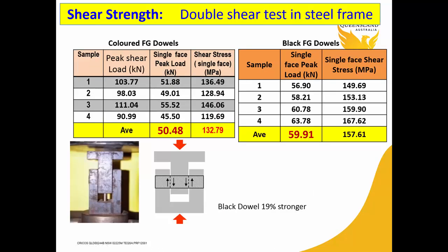Shear strength testing was also carried out in steel double shear testing, as you can see here. The difference between the guillotine box and steel double shear testing is that you have two cross-sectional areas of shearing rather than one, as in single shear testing. The sample is cut to a small length and positioned inside this hole. It goes inside the instrument, and the whole assembly is subjected to compression, and we have shear in these two cross-sectional areas.